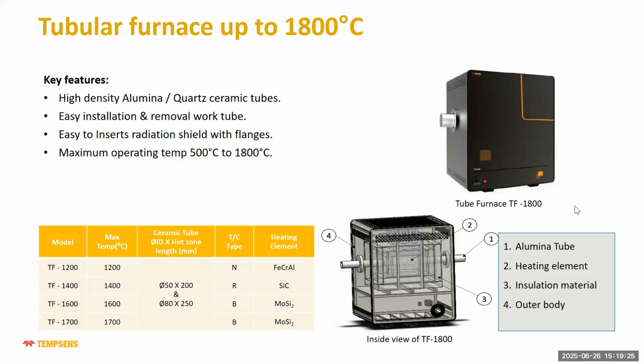The TF 1200 works up to 1200 degrees centigrade, using an N-type thermocouple and a FeCrAl heating element. Then we have the TF 1400, with an R-type thermocouple and a silicon carbide heating element. Then the TF 1600 uses a B-type thermocouple and a molybdenum disilicide heating element, and the TF 1700 uses a B-type thermocouple and MoSi2. The ceramic tube used inside the furnace can be of different diameters, ranging from 50 mm ID to 110 mm. If any customization of the hot zone length is required, we can do that too. You can see the typical inside view of the TF: the heating elements and the tube inside with the insulation.